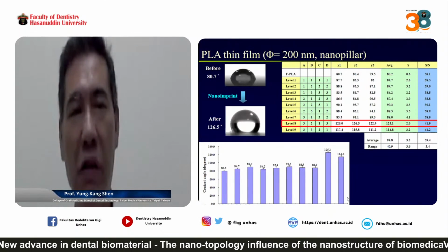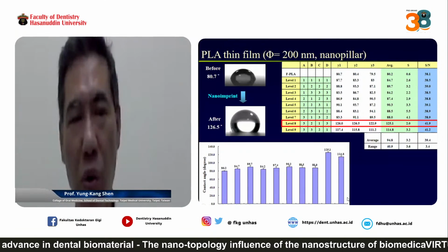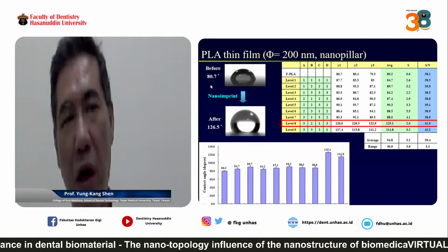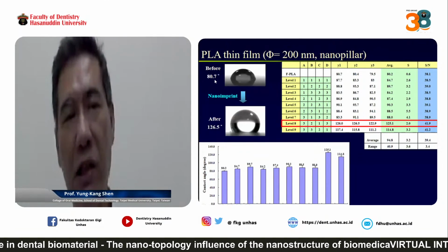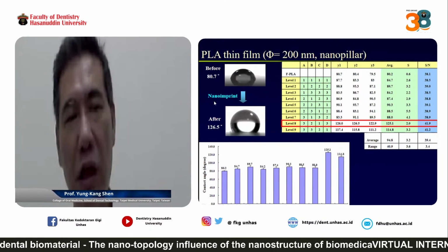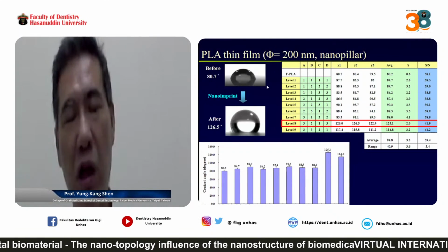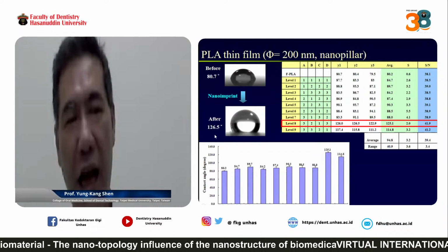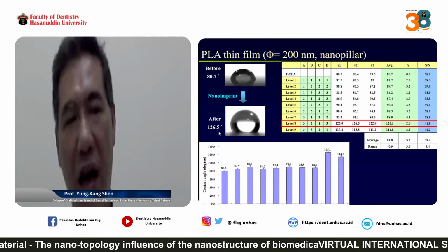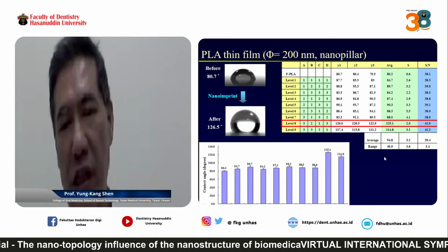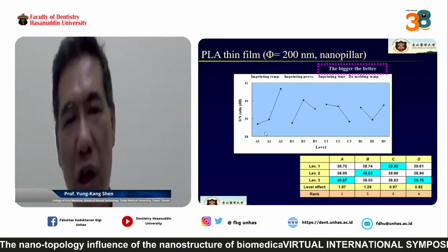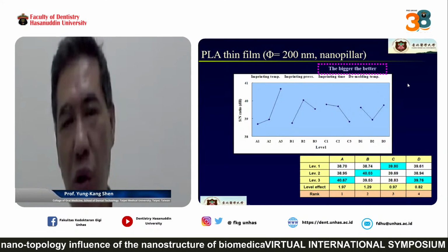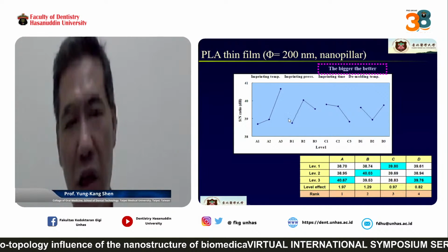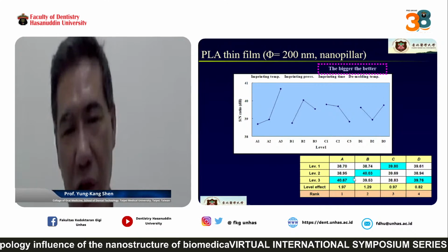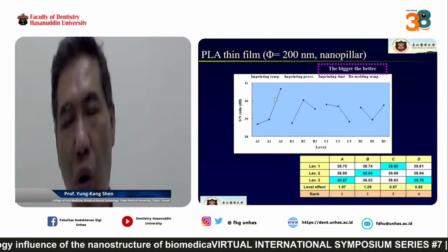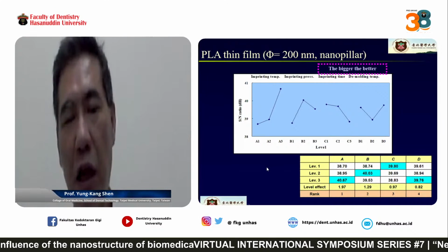This is the PLA thin film with a diameter of 200 nanometers. Also, before nano imprint, the pure PLA thin film contact angle is 80.7 degrees. After nano imprint, the PLA thin film with nanostructure on its surface has a contact angle of 126.5 degrees, so the surface properties change. Here we can also see the Taguchi method for the optimal processing. You can see A1, A2, A3 have the bigger difference, so imprinting temperature is again the most important factor in nano imprint.